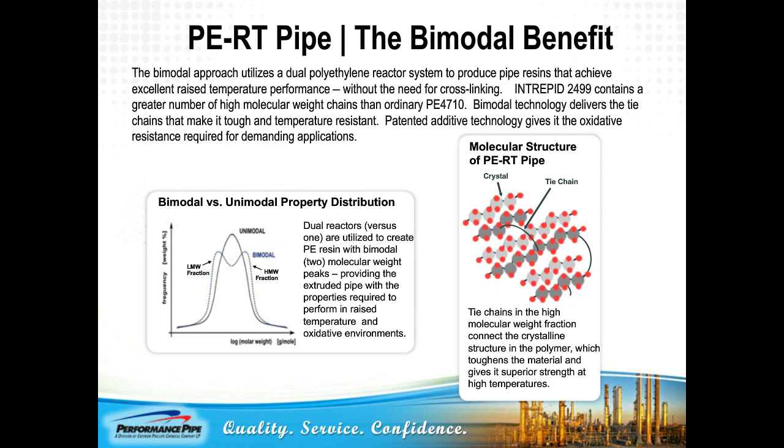By using additional co-monomer in this high molecular weight fraction, more tie chains are formed that make the resin tougher and temperature resistant. I liken this to an additional amount of stronger rebar in a concrete foundation. The resin material also contains a special additive technology that provides the greatest oxidative resistance required for these demanding applications.